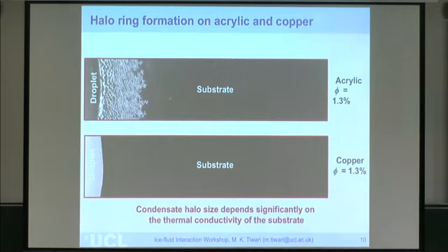What's happening here is essentially as the original droplet freezes, it releases heat, and that heat gets absorbed by the remaining liquid, which makes it evaporate, because especially when it is lying on an insulating substrate, the heat cannot go through the substrate, and outside we've got air, so it's not a very good heat transfer medium. That means most of the heat gets absorbed by the liquid, so we have vapor formation.